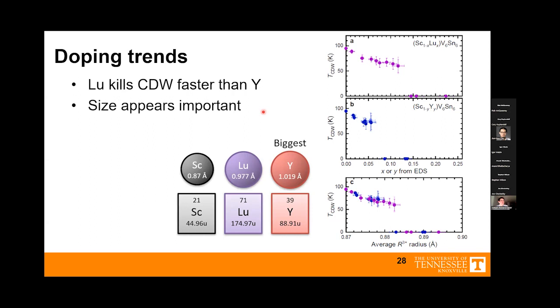So here's an interesting thing. If we simply take the average radius of the rare earth ion, I realize using ionic radius on a metal is imperfect, but I don't have a better way. But if I plot it like that, you can see that the slope of charge density wave versus average radius matches for the 2 data sets. So size appears to be more important. Doping with lutetium kills that faster.